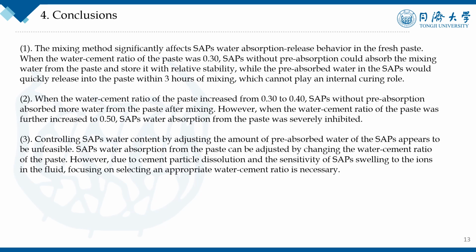Obviously, dry SAPs mixed with cement is better than pre-absorbed SAPs. However, if we choose dry SAPs to mix with cement, we need to pay attention to the water to cement ratio of the paste, because a high water to cement ratio may also promote the dissolution of calcium.